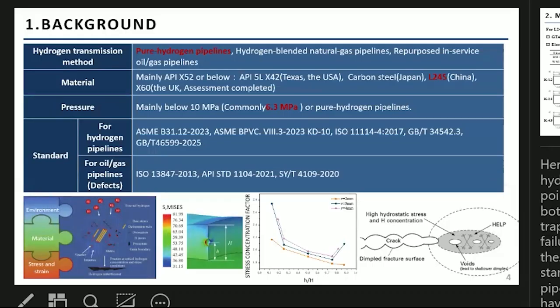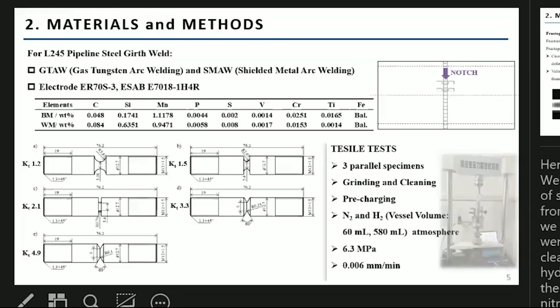For welding defects in pipelines, particularly volumetric ones, we can calculate the stress concentration for defects of varying sizes and locations. By integrating this analysis with engineering experience from pipeline operation, we can potentially establish correlations with experimental results. Actually, there are many other equivalent parameters to choose from, but here we selected the stress concentration factor that is familiar in engineering.